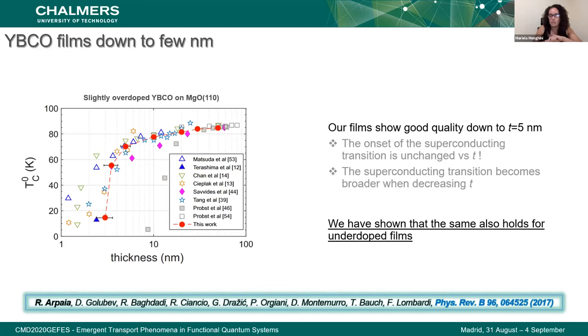Yes, this is what we have measured with resistance versus temperature measurements, because it's very stable. Then if we want to go below 5 nanometers, we need to use a capping layer of gold, even quite thin, in order to preserve the correct oxygen concentration.